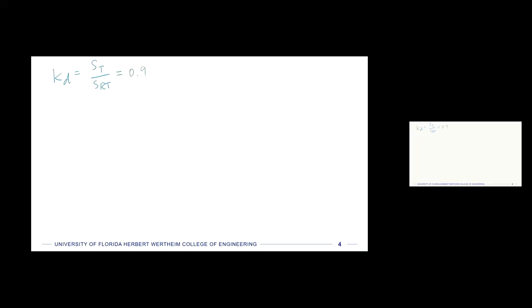So it's 0.99 plus Tc times 5.9 times 10 to the minus 4, actually that's a minus Tc times 2.1 times 10 to the minus 6. And the Tc is squared there. So it's a second order equation there.